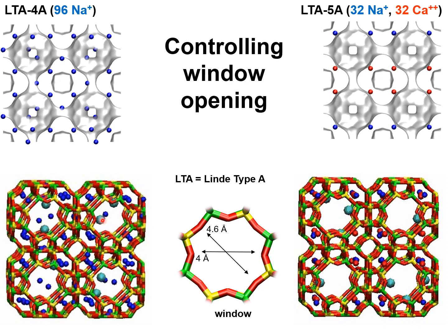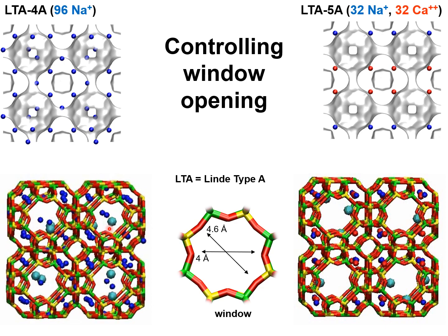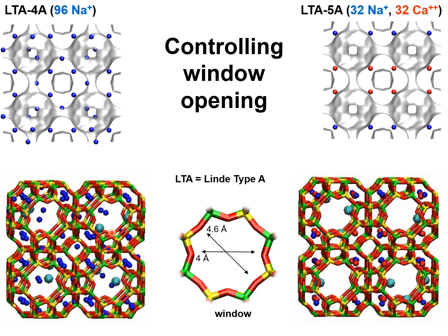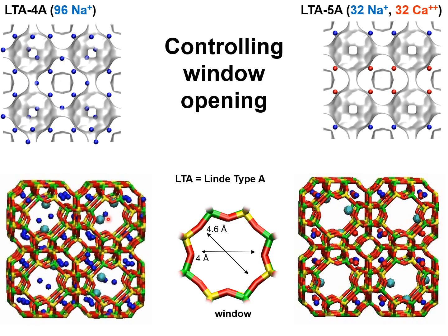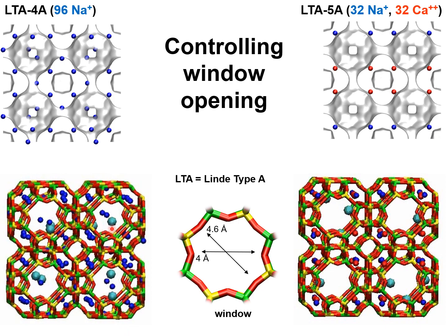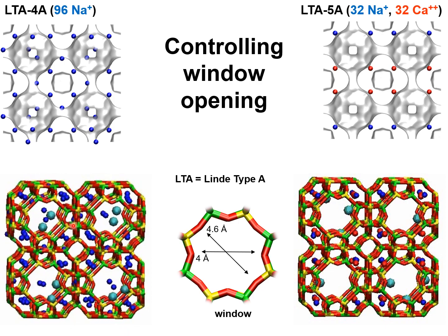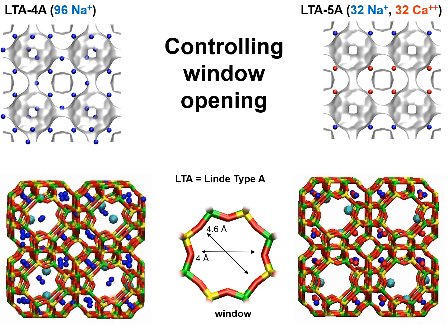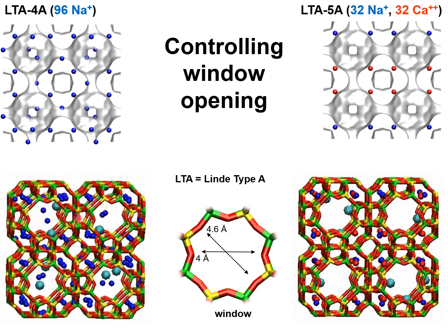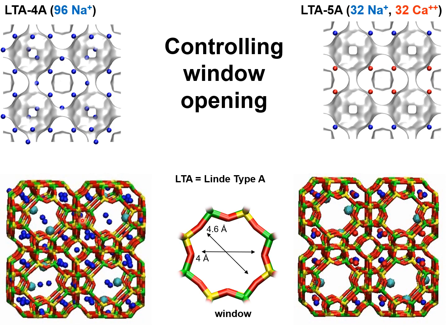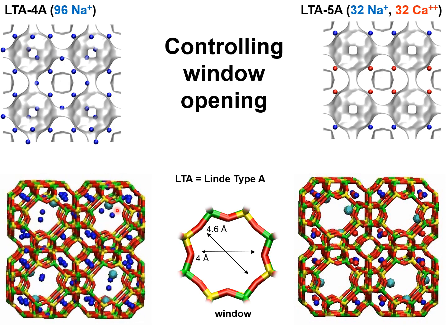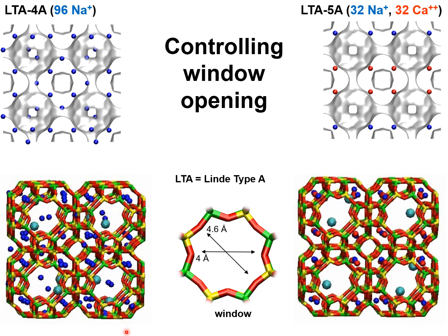Here we see the motion of methane within the cages of LTA4A zeolite. The blue spheres are the cations, and the cations are to be found in the window regions, as you can see. And due to the presence of the cations of the window region, the intercage hopping of methane is hindered significantly.